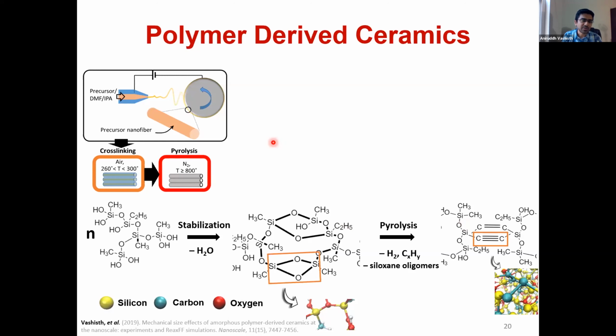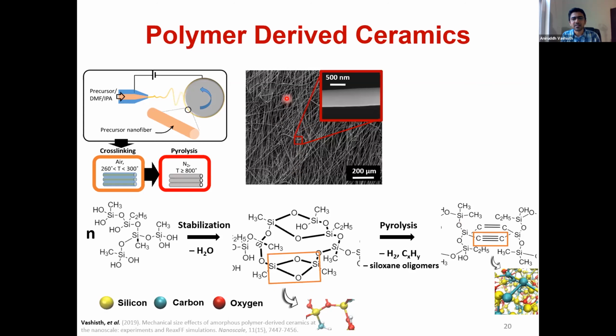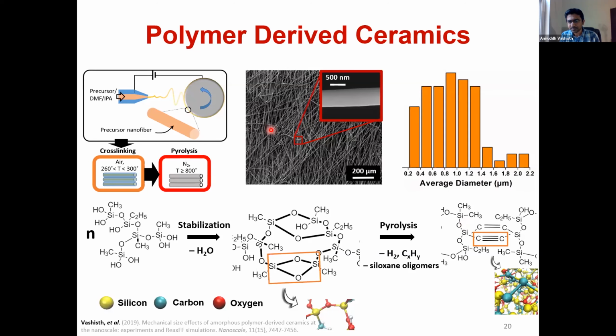So what we did was that we made a precursor using this polymer. We dissolved this in a DMF solvent, and we used electrospinning, where basically you load up all this precursor in a syringe, and then you apply a potential between a syringe and a collector, and you basically make fibers using this process. We made fibers which had average diameter close to 1 micrometer. But as you can see here, the diameters actually varied from 200 nanometers to 2.2 micrometers. There was a wide variance of nanofibers that we got.